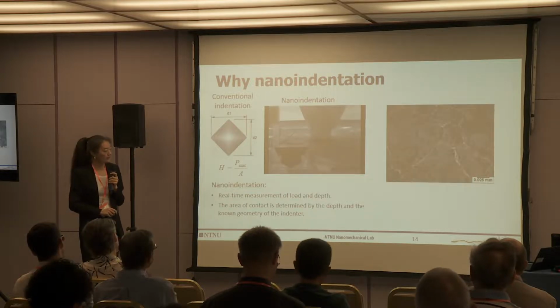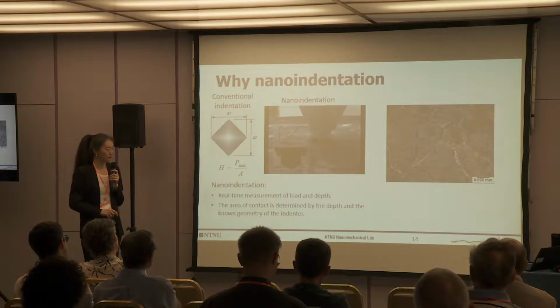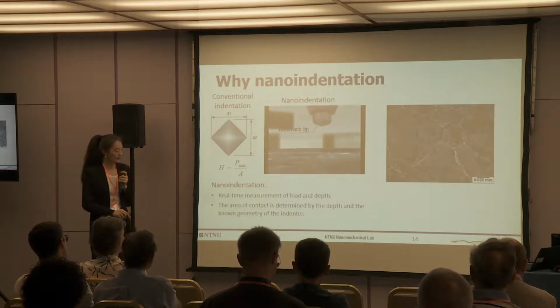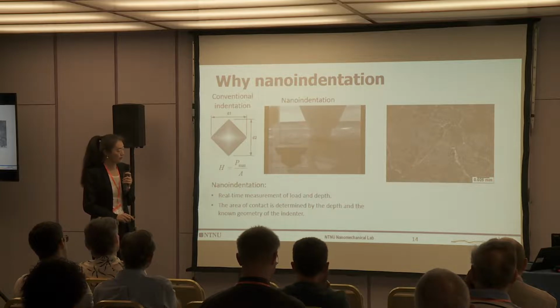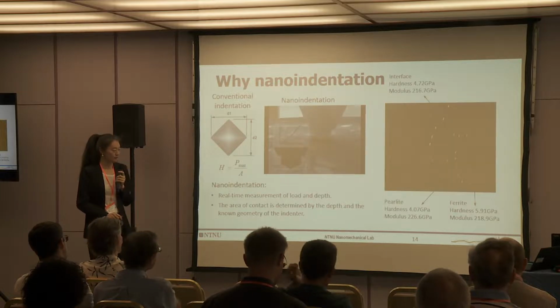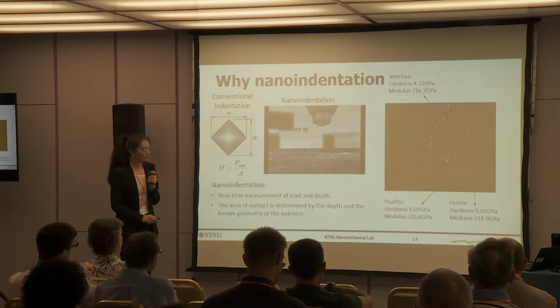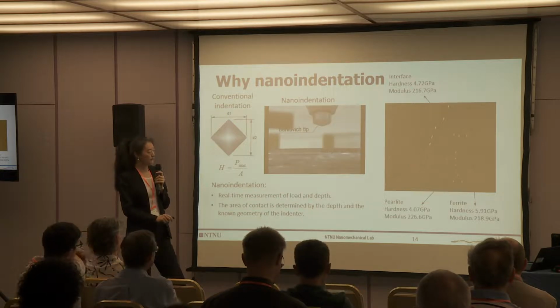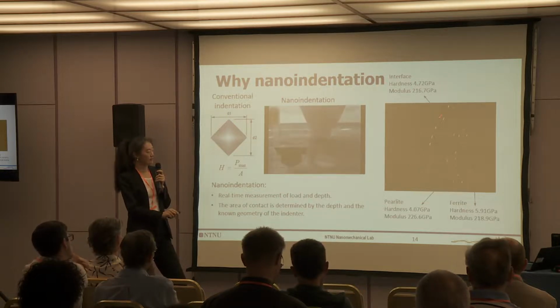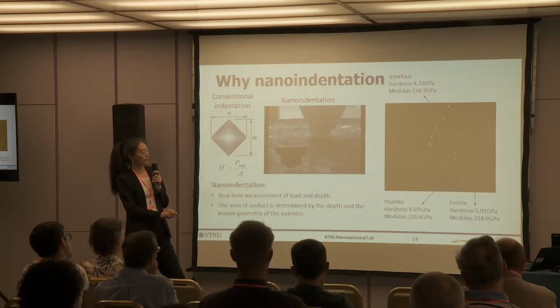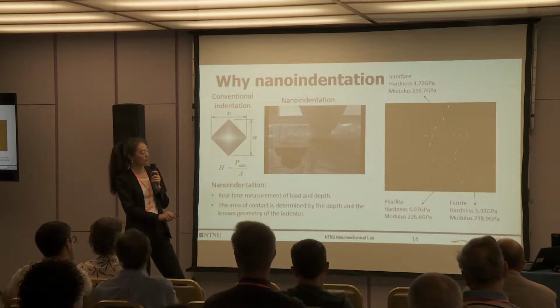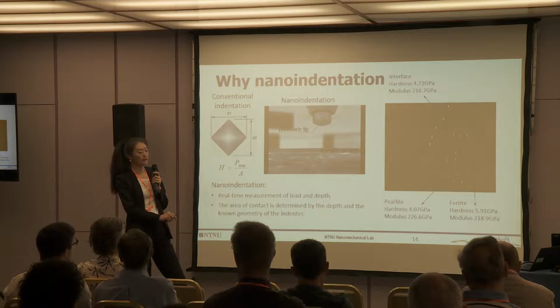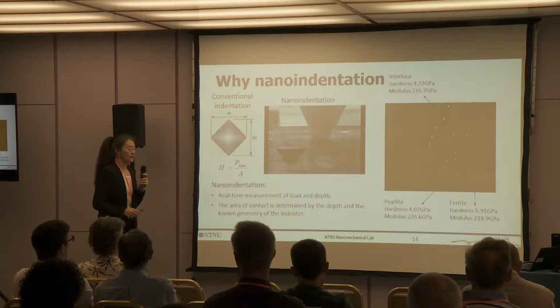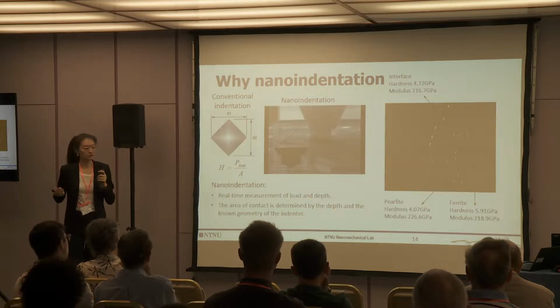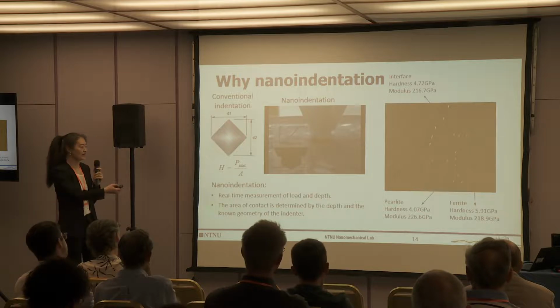I have one example using indentation for individual phase investigation. This is just a micrograph of the wheel steel. It includes different phases. By indentation, we are able to distinguish the pearlite or the ferrite phase and even the interface between them. And you see that we easily get the mechanical properties of each individual phase and their interface. So think about the inhomogeneous microstructure of AM-ed materials, and this is almost the perfect tool for that.